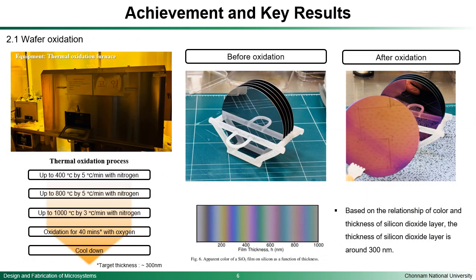We had the wafer oxidation for our first fabrication process, and it can be seen from here that the silicon wafer changed the color from black into some gradient color, and by matching the color RGB value, we can have the silicon dioxide layer thickness, and it's around 300 nanometers.